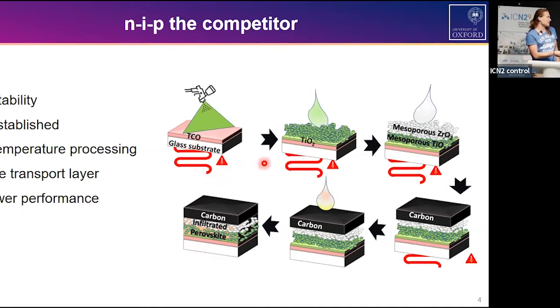It's very well established in the carbon electrode field and has been shown to deliver on the stability promise of carbon, and has three mesoporous layers. One is the TiO2 ETL, one is usually a mesoporous insulating layer, and in this configuration the carbon is also mesoporous. But these mesoporous layers are usually produced at really high temperature, and that's why most of these architectures don't have an HTL, because most HTLs are temperature sensitive, as is the perovskite. That's why in this case the perovskite is infiltrated later into the cell. A high temperature process is usually less scalable in industry, and you cannot do it on flexible substrates, one of the things that are really promising for perovskite solar cells.